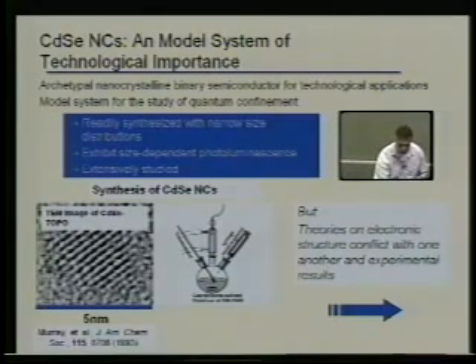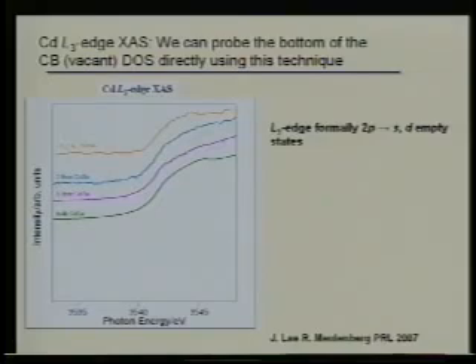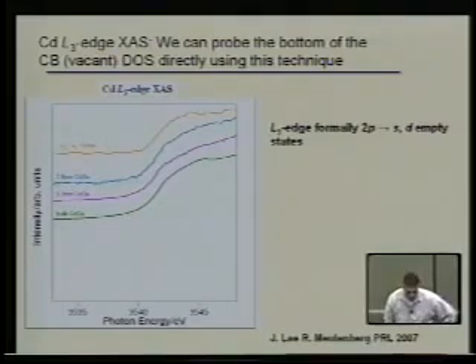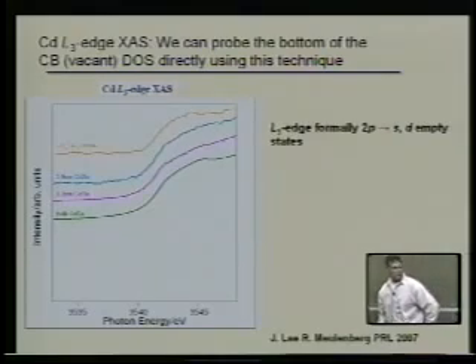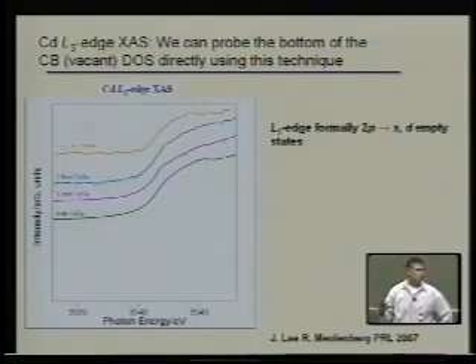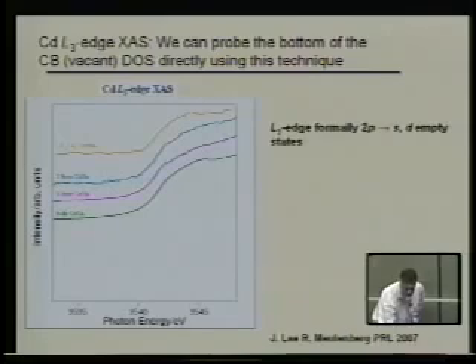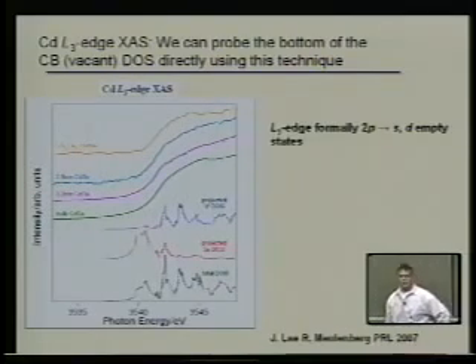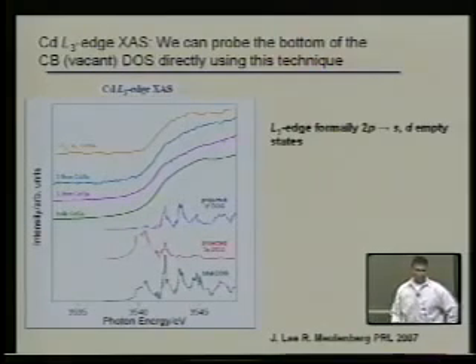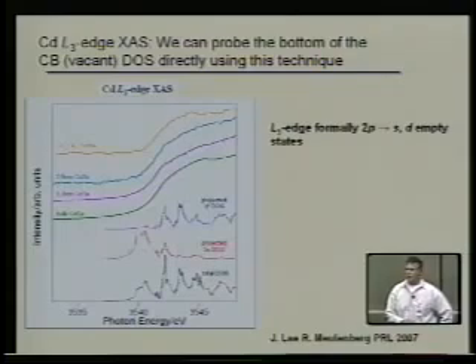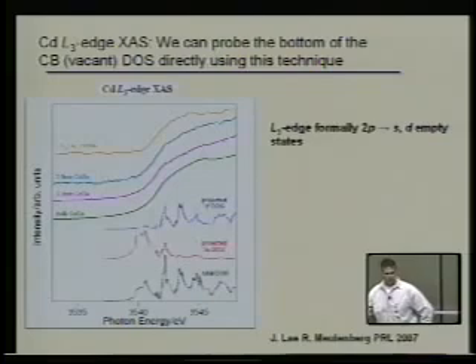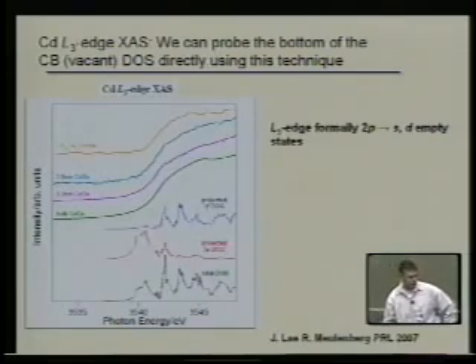And this is a really nice use of NEXAFS. So if we just look at this as is, we say, well, OK, maybe not much is happening. So we're going from bulk cadmium selenide, to 3 nanometers, 2 nanometers, to one of the smaller clusters. Now we're doing this from the cadmium L edge, and we know the cadmium L edge is measuring both S and D-type states. So we do a calculation of the densities of states, what should happen in the cadmium selenide, and we see that at the bottom of the conduction band, it should be primarily S-type states, whereas higher up in the conduction band, it's primarily P-D-type states.